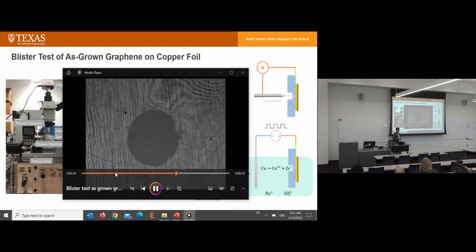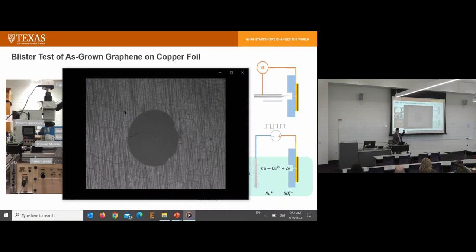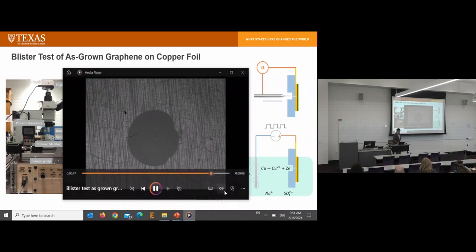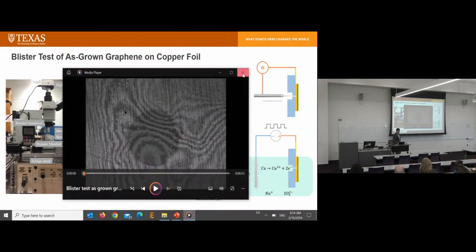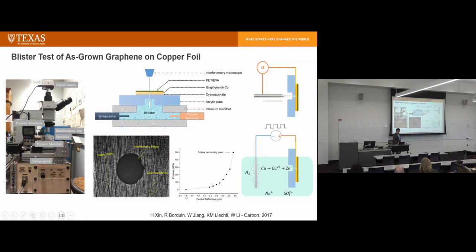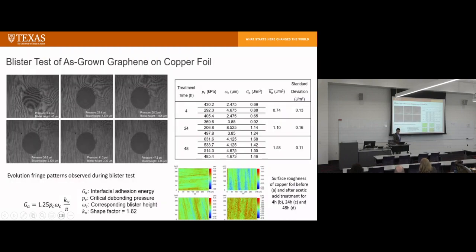And then at the last moment, it's going to delaminate. So the fringes will disappear, and at that moment, you calculate the final height, and you use that. Yeah, that's when it's disappeared and failed. So that's delamination, and you use that to calculate. So this is a central deflection, and this is the pressure you introduce, and using the pressure and the maximum height, you can find out